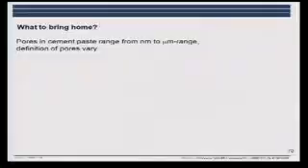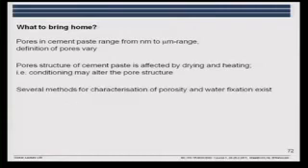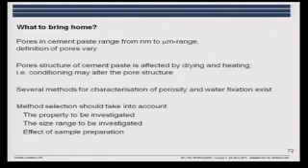So, in summary, we have variation in pore sizes from nanometer to micrometer, and we have the definitions varying. The pore structure is affected by drying and heating. So you need to consider that, both when undertaking work yourself, but also when you're reading papers and using data. There are several methods which can be used to determine both pore structure and water fixation. When you are selecting the methods, you should consider the property you want information on, the size range you want to measure, and then possible adverse effects. I would suggest that in many cases you would use a combination of methods.